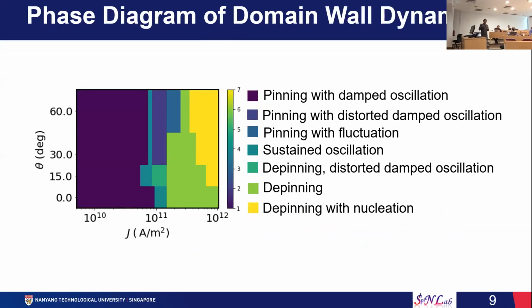Now all these features are included in this phase diagram, where we explored the domain-wall dynamics over a vast range of current density, from 10^10 to 10^12 ampere per square meter. We observed different types of regimes, as indicated by the seven different colors: different types of pinning, some oscillations, depinning, and depinning with nucleation.